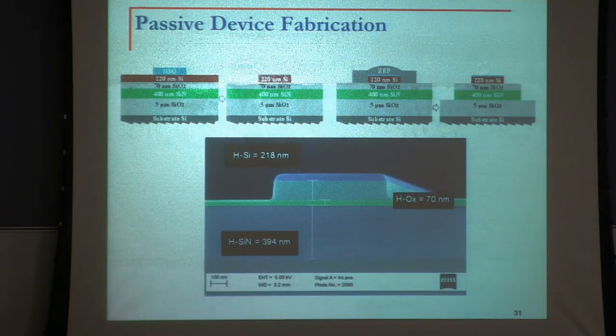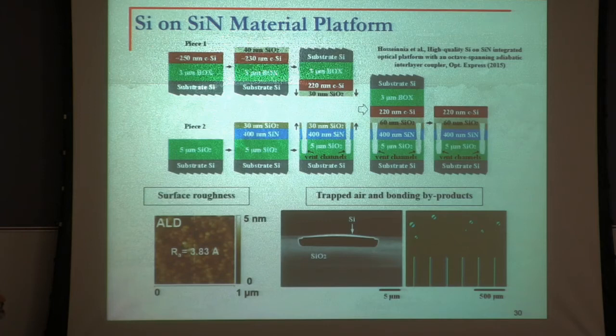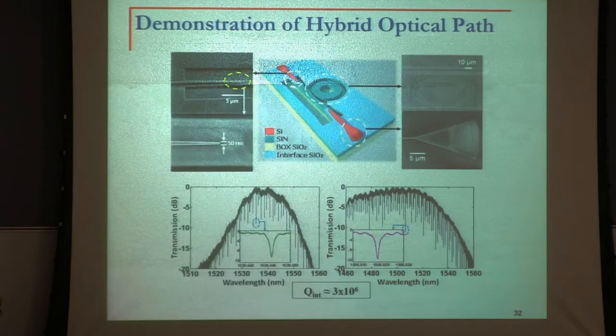This is the fabrication process. So we first fabricate our devices in silicon, which are smaller because of the higher index. And then we come back and fabricate devices in nitride. So the key advantage of our technique is that the material development is done all prior to any fabrication process. Because the deposition of nitride is always at high temperature, it will affect silicon. So this way, we just develop the material using this technique first, and then we will fabricate our devices.